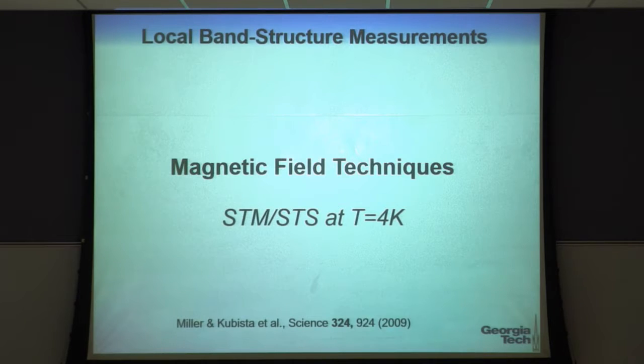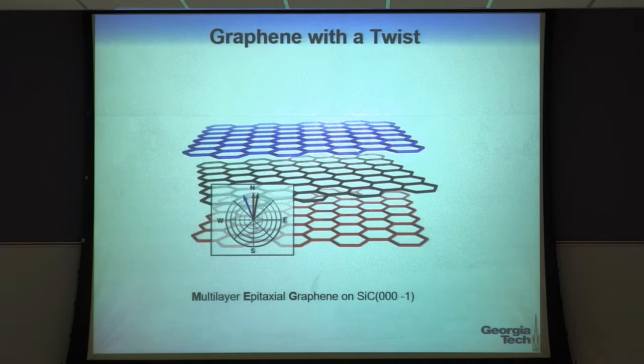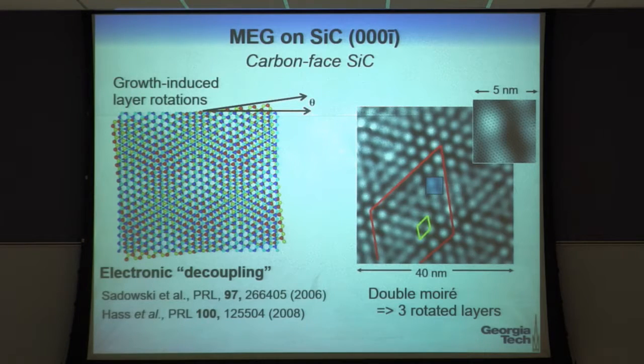If you have a magnetic field available, and we did, that would go to about 8 Tesla, then you can start studying things with even better K resolution. So the sample that I'm going to tell you about is graphene, which is stacked in this manner. It has twists, little rotations between layers. Happens to be the way it grows on top of silicon carbide in a particular fashion. If you zoom in, you can see this is the atomic structure, so this is the graphene lattice, but that little modulation is a consequence of the moire pattern that occurs due to the interference of the crystal structure of one layer on top of the other.